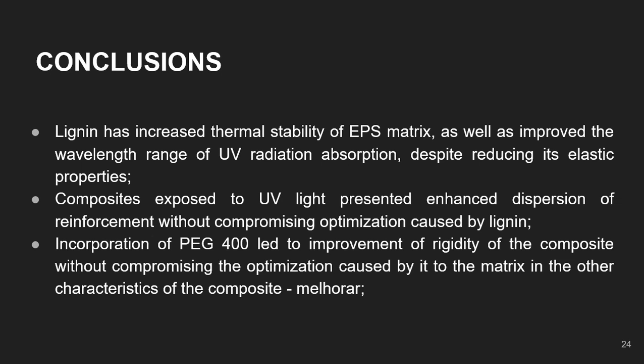in order to produce new hybrid materials with optimized properties may prove to be a viable way of combating their inappropriate disposal, since from the combination of EPS with lignin, it was possible to produce a thermally more stable composite than its precursors, with an absorption wavelength range wider than that of EPS, capable of absorbing within the UVA radiation spectrum, and whose mechanical properties can be balanced with the joint use of PEG 400 without compromising the other characteristics, and which can still be optimized by photochemical treatment.